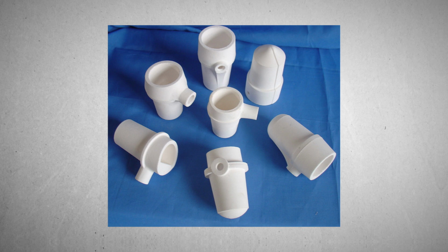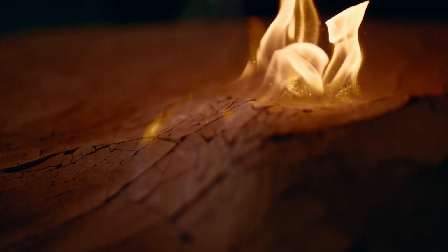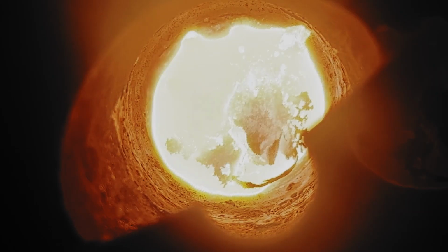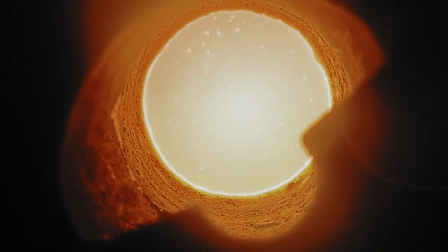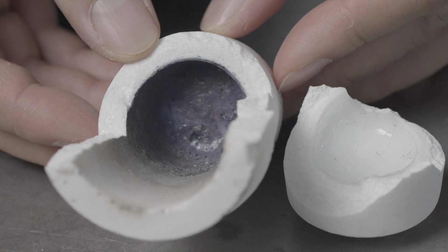And to sum it up, our standard silica ceramic crucibles are a great commercial choice for our regular platinum casting operations. But that crucible is not going to be able to withstand high heat over long periods of time, especially at platinum alloys' melting temperature. So please do use it with care. Don't overcook it. Don't superheat if you don't have to. Don't hold that platinum molten in that crucible for too long. And definitely do not use the crucible until it's reaching its breaking point.